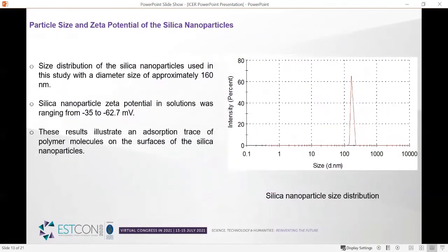So particle size, we also looked at the size of the nanoparticle, and it was mainly 160 nanometer. We also looked at the zeta potential, and we saw that the polymer adsorbs on the surface of the nanoparticle, which is interesting. And we actually saw a trace of this adsorption from the voltage of the zeta potential. However, we couldn't quantitatively see this adsorption in the UV vis, so we neglected this in the adsorption calculated.